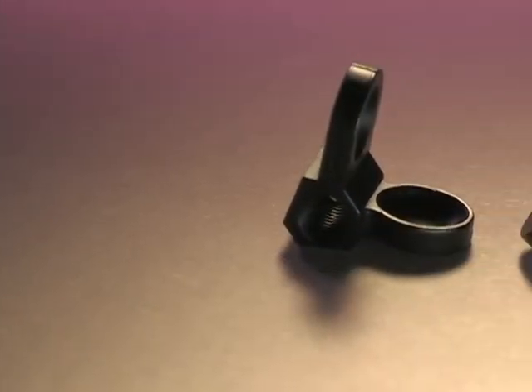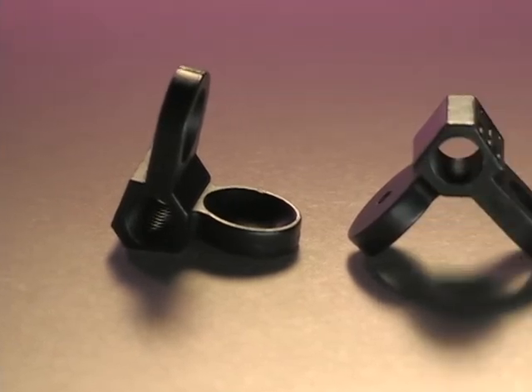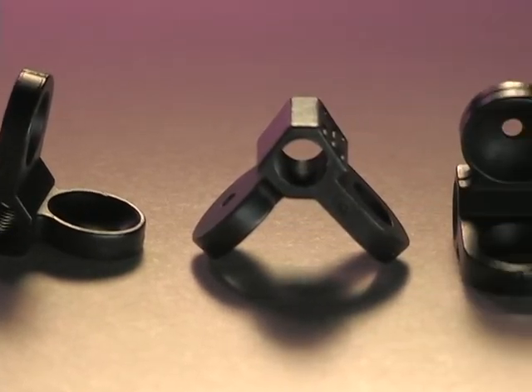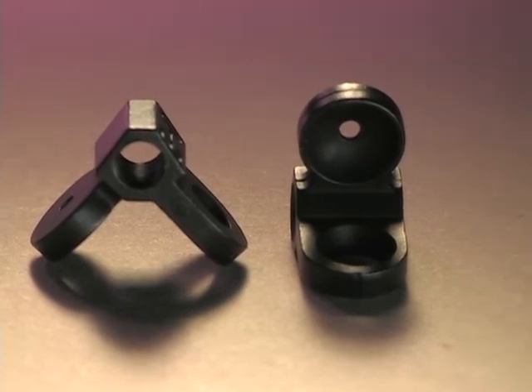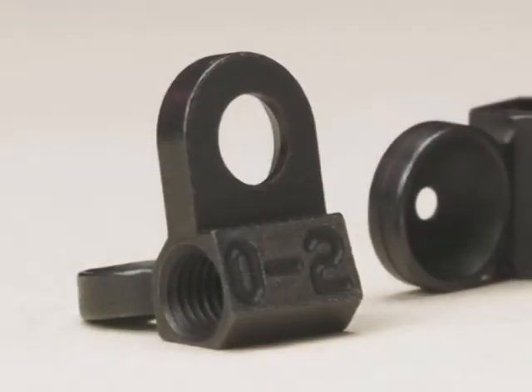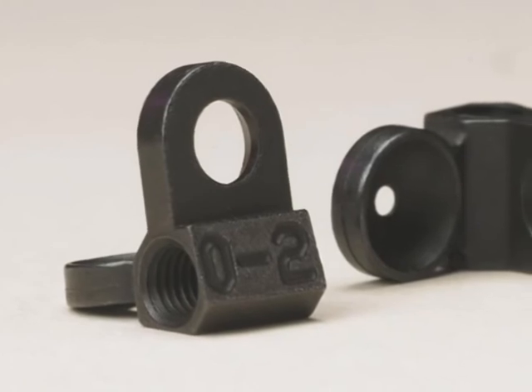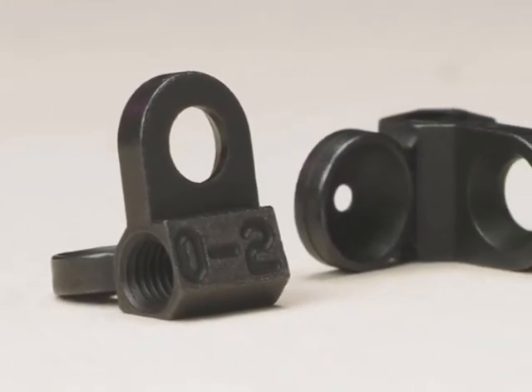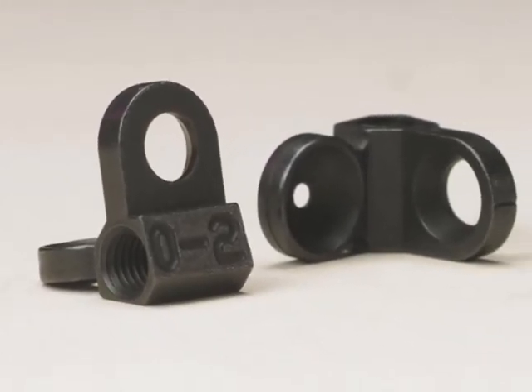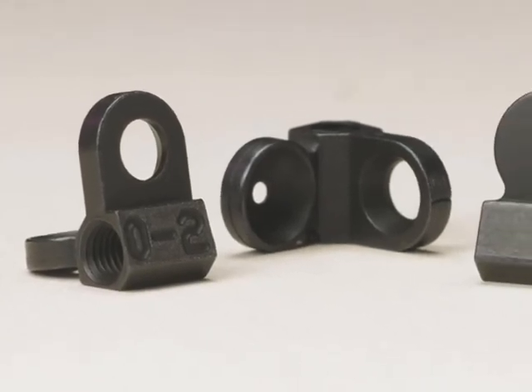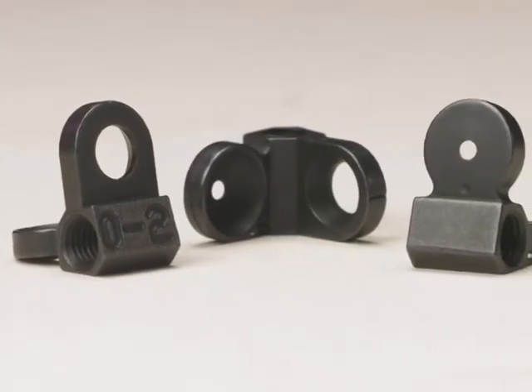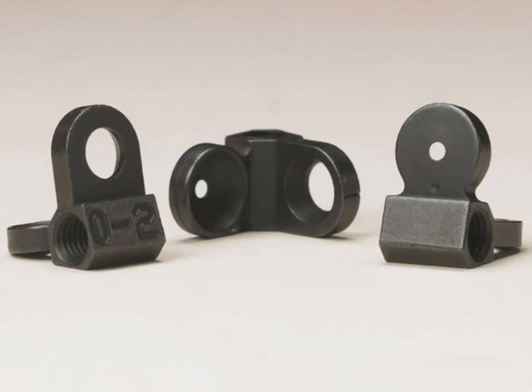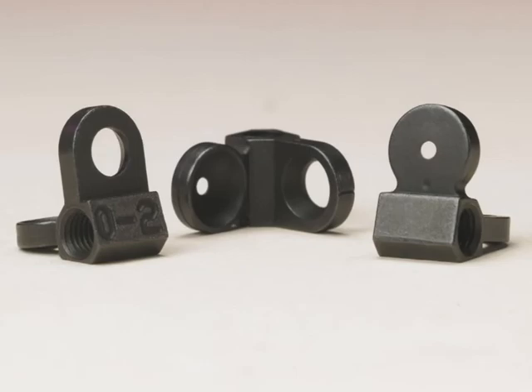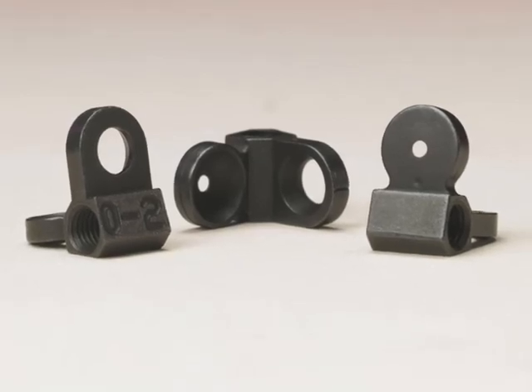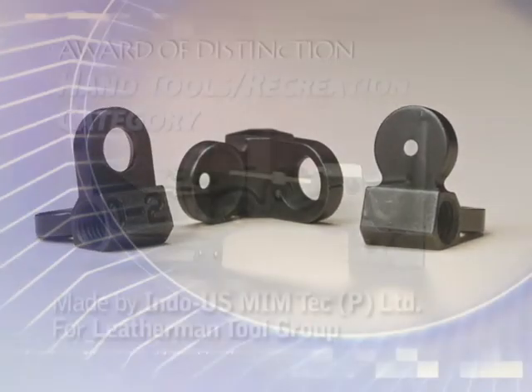The sight allows the shooter to target objects at ranges up to 200 yards by using the larger aperture, and to target objects at longer ranges by flipping the sight down and using the smaller aperture. The part is made to a density of 7.5 grams per cubic centimeter and has an as-sintered ultimate tensile strength of 55,000 psi. Choosing the MIM process over investment casting provides a 40% cost savings. Secondary operations are limited to tapping and a nitride finish.